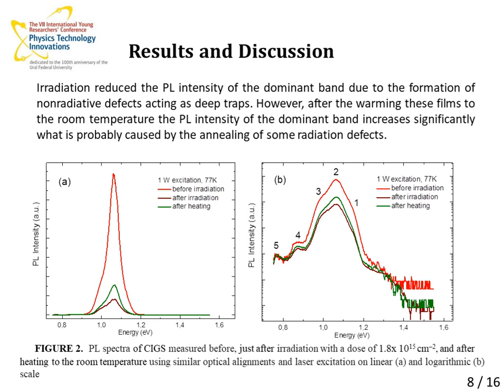Irradiation reduced the photoluminescence intensity of the dominant band due to the formation of non-radiative defects acting as deep traps. However, after warming these films to room temperature, the photoluminescence intensity of the dominant band increased significantly, which is probably caused by the annealing of some radiation defects. It can be seen on the logarithmic scale that the spectra contained 5 photoluminescence bands.